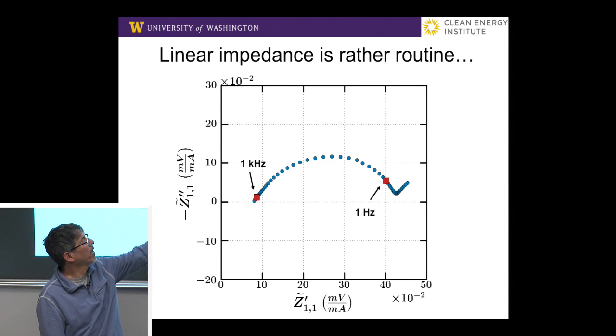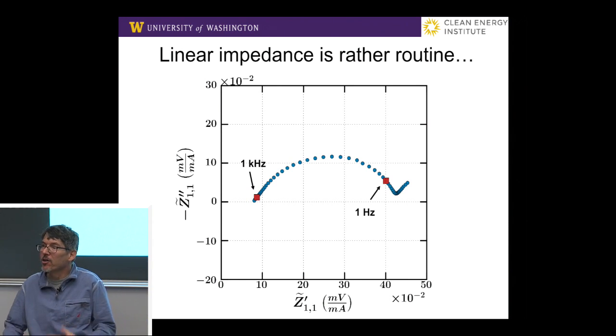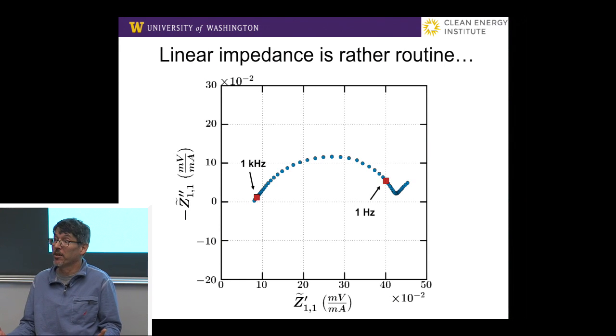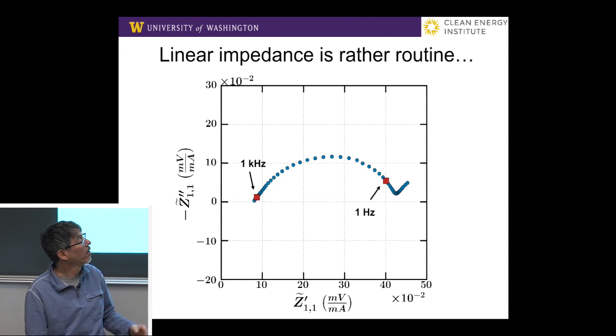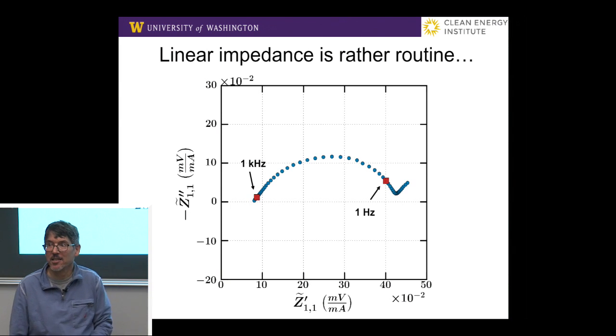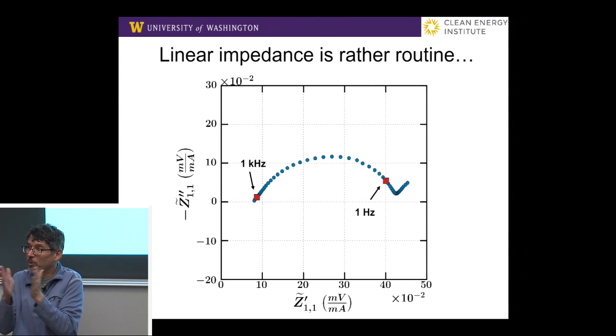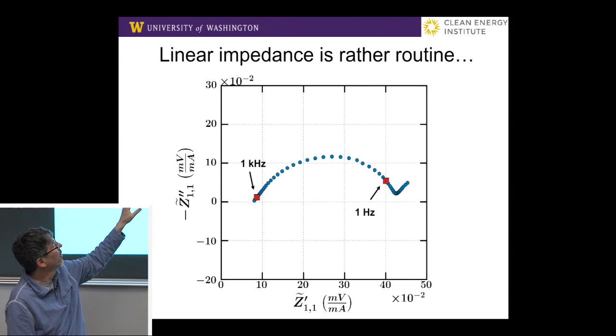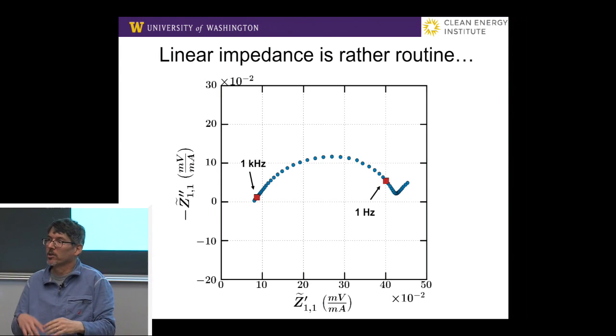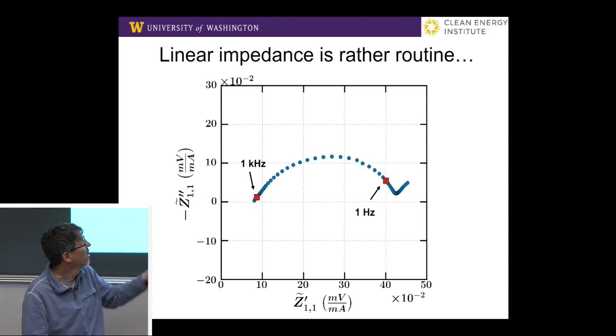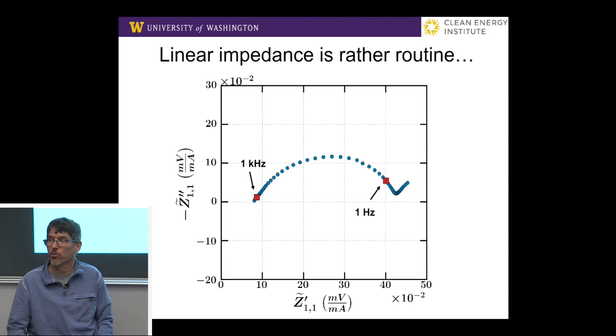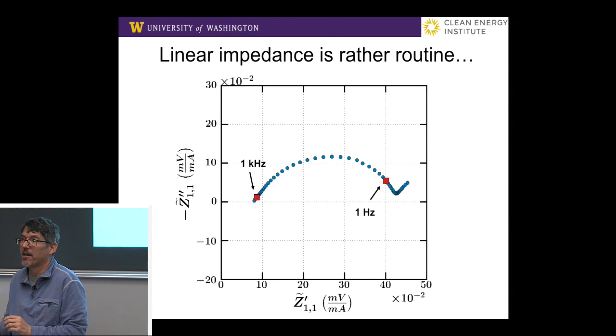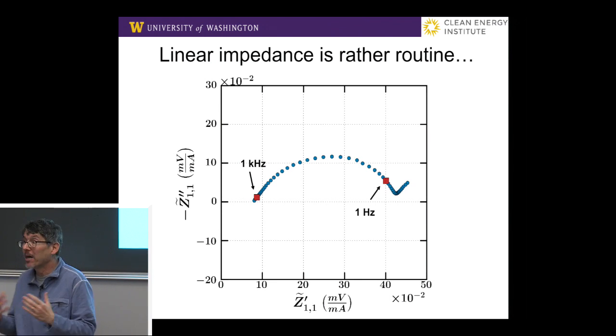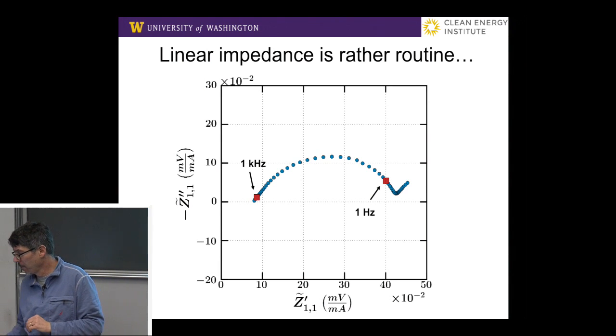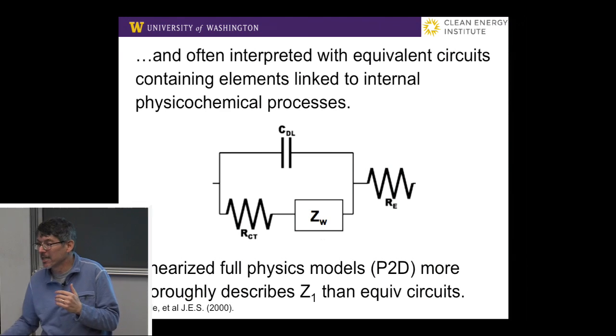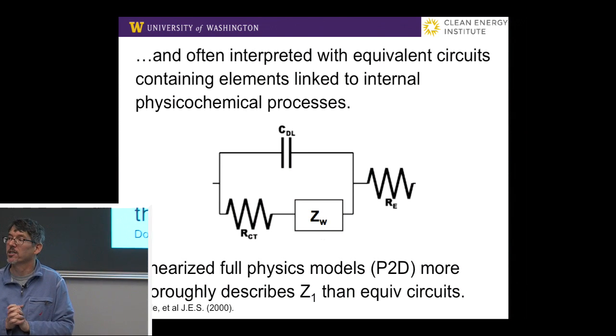The characteristic frequencies I'm showing you give you a sense of different time constants within the battery itself. Low frequencies off to that side are transport processes within the battery. The arc, if there's one or two arcs, is related to charge transfer typically. The offset from 0 is related to resistance in the electrolyte as we go to high frequency. There's a bunch of stuff we can learn from the linear impedance. The way we normally interpret it is kind of the way I was just saying.